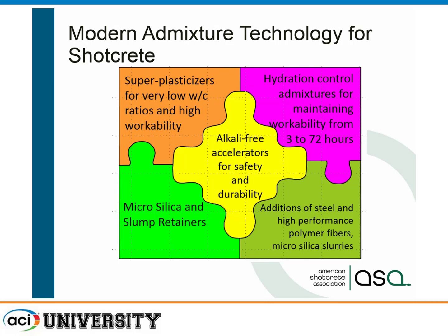We use certainly superplasticizers, high-range water-reducing admixtures, so we can maintain low water-cement ratios and still get it pumpable, workable through the small hoses that we use. We use alkali-free accelerators. Microsilica is really popular. Microsilica is great for reducing permeability and chloride ion penetration in your repair materials. We use steel and synthetic fibers. And a lot of our contractors are using hydration control. This is where you can actually put the concrete to sleep for up to 3 days. We don't need that much, but it gives us much longer than the 90-minute window that's typical for concrete from when it gets water added to when it is put in place.